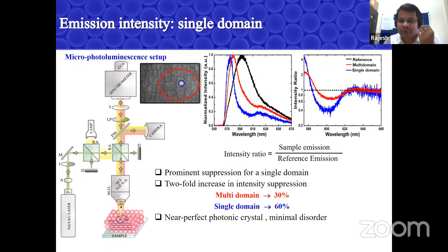So to give a very clear picture of this result, what we do, we take the intensity ratio, basically your emission from your sample and your reference emission. And if your sample does not change the emission properties, it looks like a reference sample only, you get 1, because your sample does not do any changes to the emission. But if the intensity ratio goes below 1, that means emission from the sample is suppressed. So that's what is shown here.